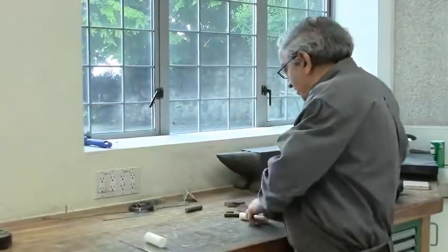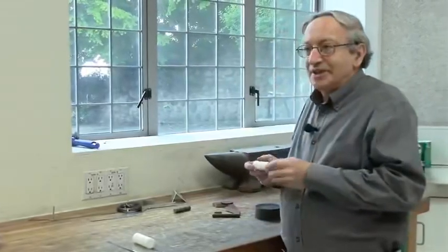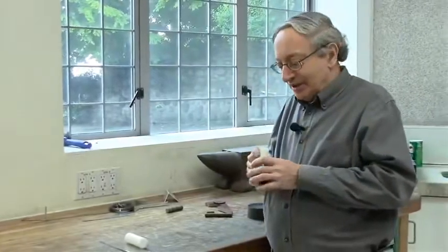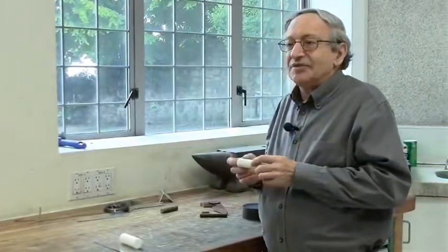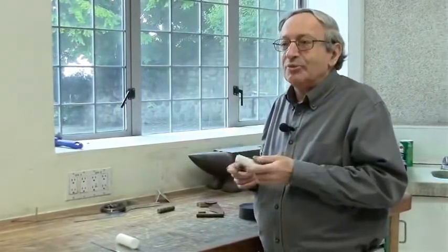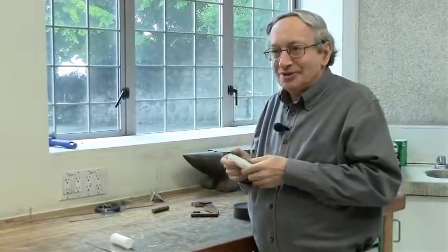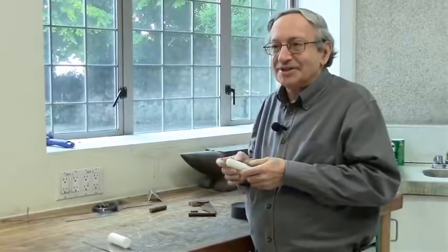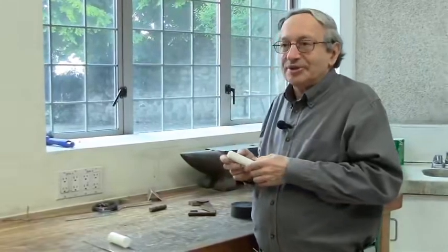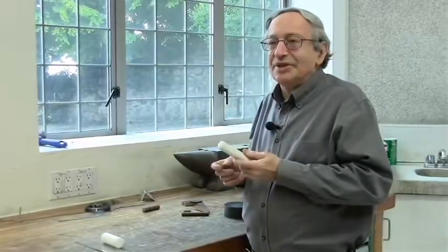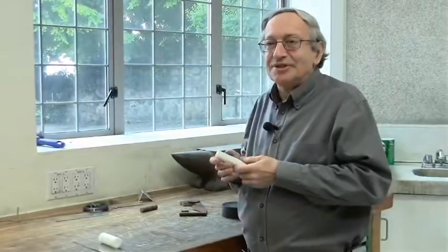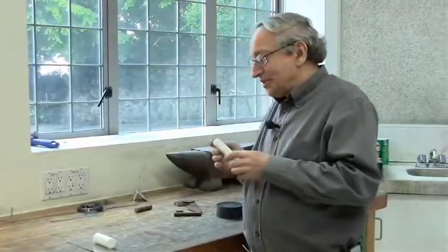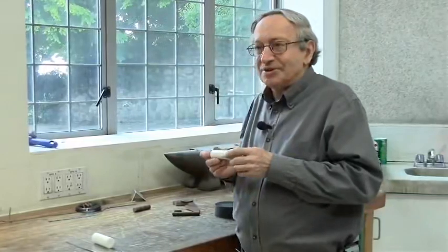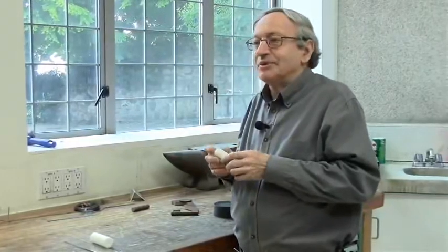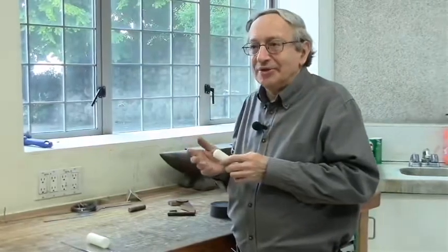Now, another material which has good lubricity is Teflon, that you all know well. Teflon also stands a fairly high temperature. It's usable to almost 200 degrees C. It's a weak material. It flows, cold flows. It's weak. It doesn't hold threads. It has very good electrical properties. It's heavily used in RF work if you need some coils, anything to do with high frequency. But it's actually not a very useful plastic because it's too weak. I use it sometimes for bushings which don't have to be highly loaded.